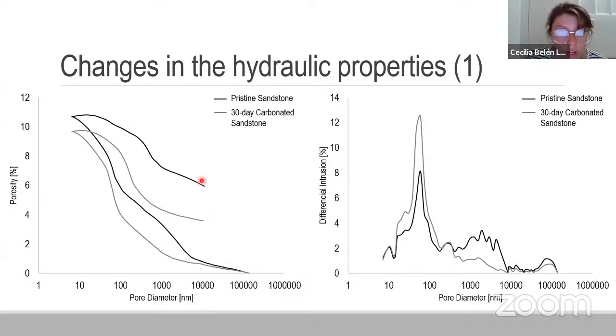What we can observe is that after carbonating the sample, the amount of mercury that remains inside the sample is less, which means the amount of ink bottle pores reduces after the carbonation process.